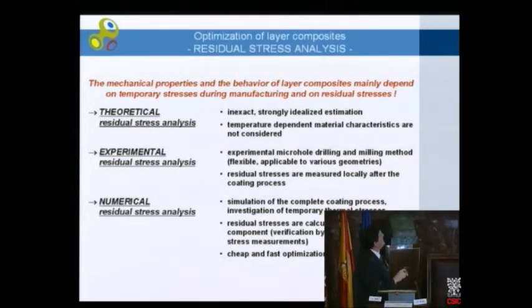Okay, as I mentioned before, we have to overcome this problem, and therefore it is essential that we not only understand the final result, but also measure the temporarily occurring stresses during the various manufacturing steps and the residual stresses. Both groups have to be investigated. And therefore, we need the theoretical background, and again, we need the experimental setup, and we have to match it with the calculations by numerical stress analysis.